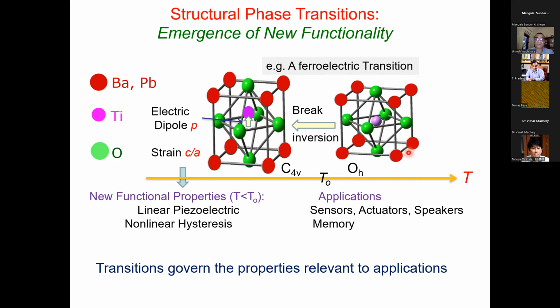It's a very beautiful structure. The barium cation at the corner of the cube and titanium cation at the center of this oxygen octahedron. And as you lower the temperature at a transition temperature T0, this crystal suddenly breaks inversion symmetry, and this breaking of symmetry arises from, or is associated with, off-centering of this titanium atom from its central position.